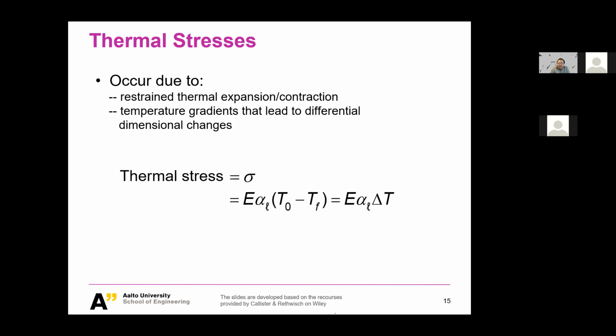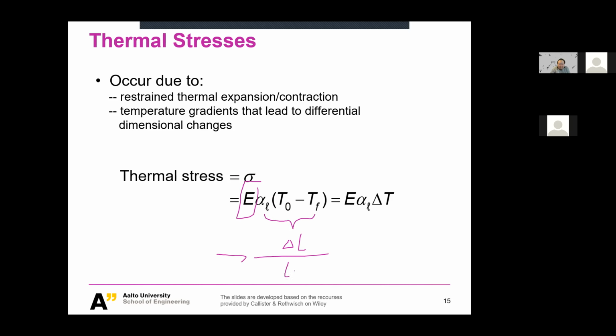And we could actually use the simple Hooke's law here. As you can see, the stress is equal to E, assuming everything is isotropic, times delta L divided by L0, right? This gives you an estimation of the thermal stress we probably could have. And finally, you could calculate it in such a way. This is the stress you could use to make an estimation, but you should think about how this stress could be really detrimental if it is very close to plastic deformation, and even more severely if it is close to the failure stress that your material could have.